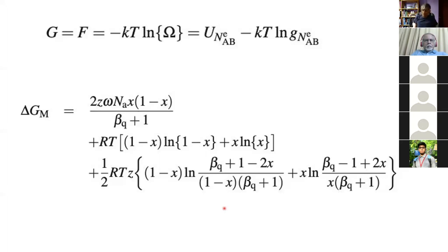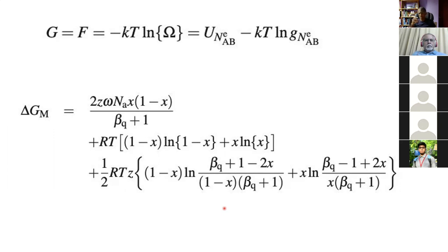Another reason: much thermodynamic data is derived at high temperatures, so extrapolating those functions to low temperatures can yield strange results. Quasichemical theory enables rigorous extrapolation to low temperatures — below about 600°C for nickel and iron systems. For calculating transformation start temperatures for non-equilibrium transformations like martensite and bainite, we use quasichemical theory for extrapolations because it is rigorously founded, accounting for non-random configurational entropy.